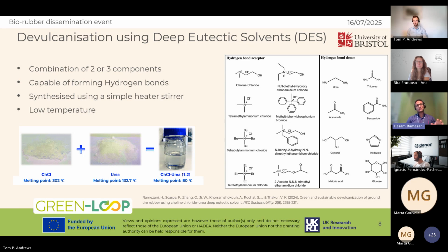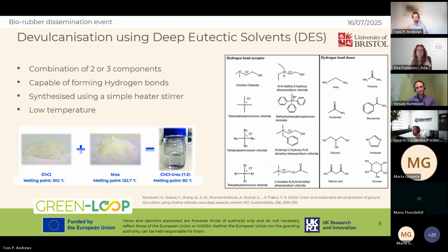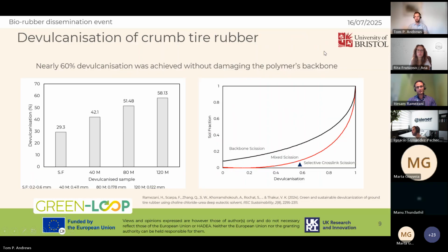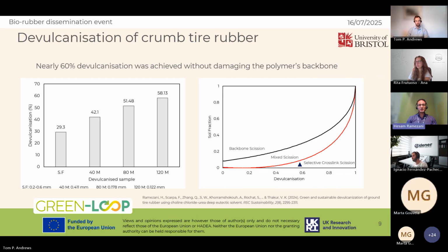So this is the solution that we use alongside low power output sonication, ultrasonication, to devulcanize the crumb rubber. Next, please. Here you can see the trials of the devulcanization. We used 4 different crumb sizes, the tire rubber that Tom mentioned, and the sizes ranged from 0.6 millimeter to somewhere around 0.12 millimeters. And the highest percentage that we achieved was 58.13 for the smallest size of crumb rubber.